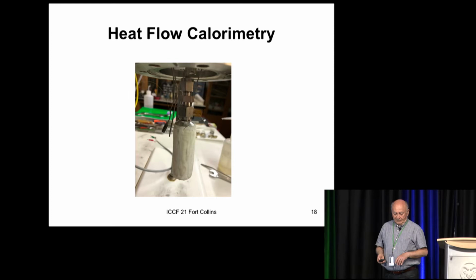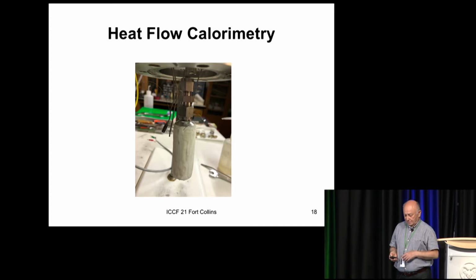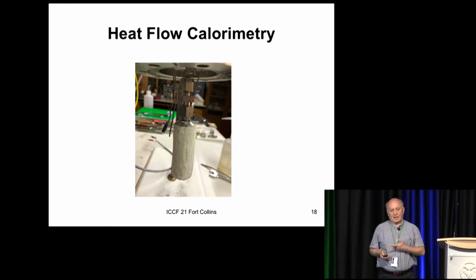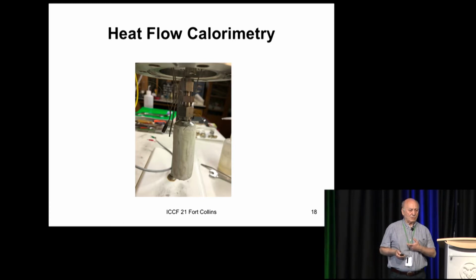And I have a thermocouple that goes inside, and I can evacuate the powder, and then put, again, hydrogen, and heat it to, so far I went to 600, 700 degrees, but this is stainless steel, and stainless steel has a problem that hydrogen at these temperatures start diffusing out. So in the future, I will go to quartz, because quartz is better. Could stand maybe 1,000 or 1,100 degrees.